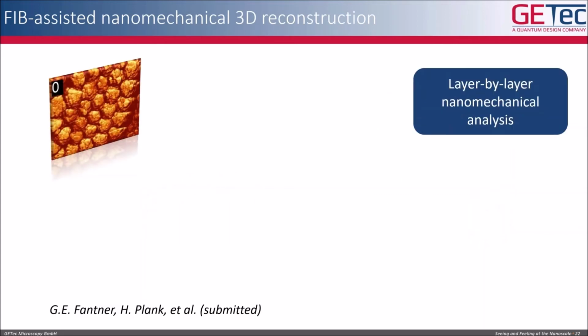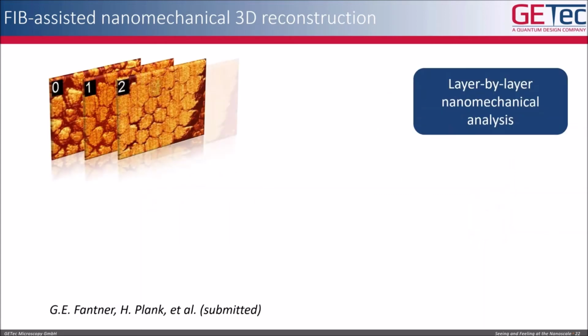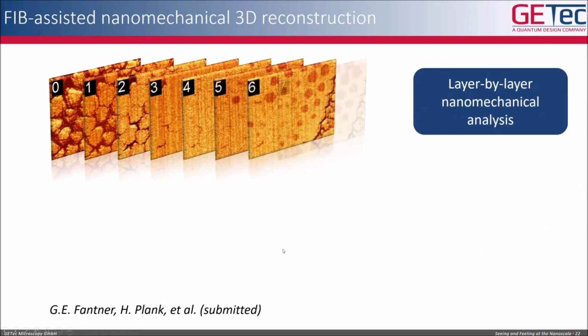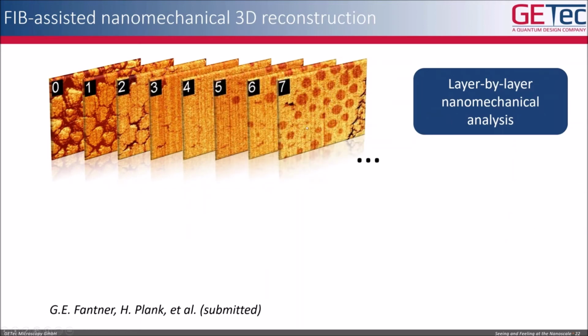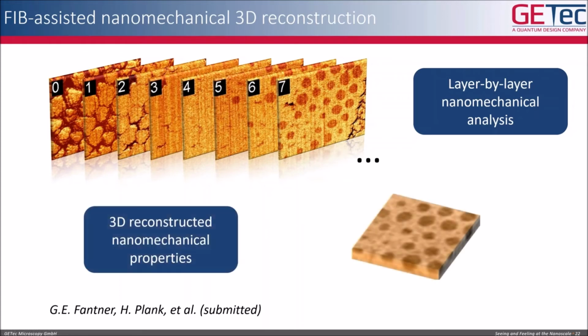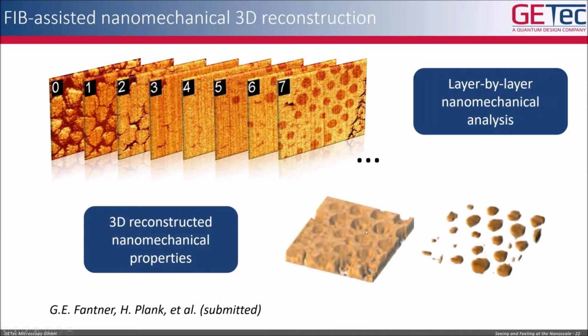And the results you see now here, so we took a series of 8 different images. And what you're seeing here now is not the topography in the AFM images, but really the mechanical properties, so the elastic modulus. And you can use this data to make a 3D reconstruction of this sample, and then make a deconvolution, which beautifully shows you the softer polymer parts and the harder beads that are encapsulated inside this polymer.